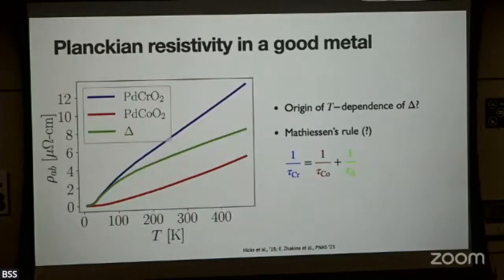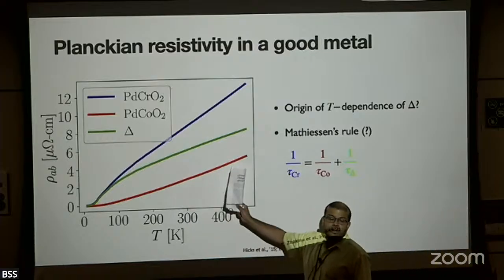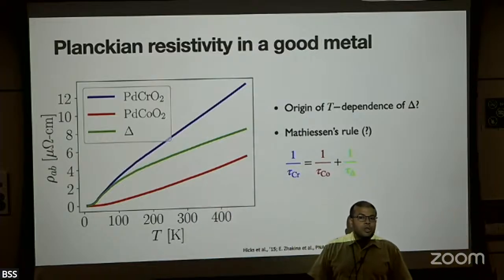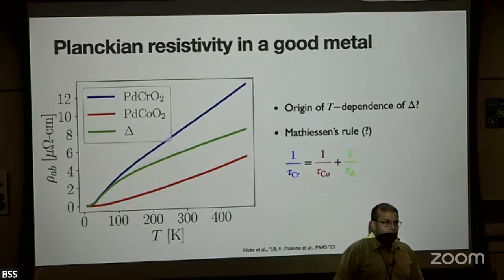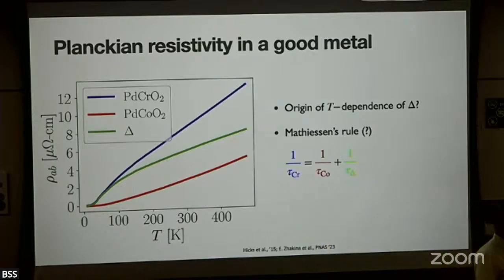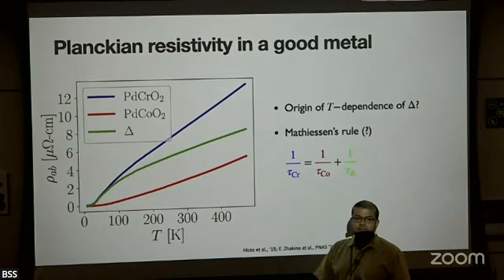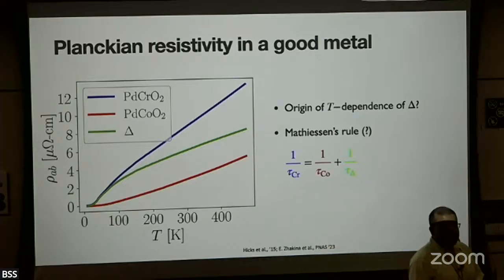Oh, okay, I guess my slides got switched. You look at this other compound, the sister compound, which does not have the local moments. So that's the red curve here. Okay, so the phonon spectra are almost identical, but their resistivities differ by quite a bit. And the chromium compound is the one that exhibits a T-linear resistivity.